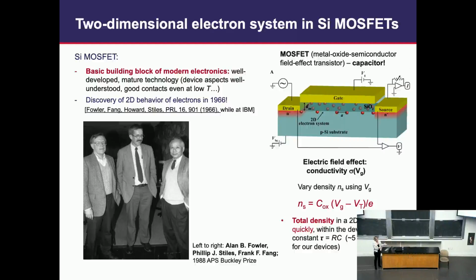And this can be done very quickly. In our case, the longest time is 5 nanoseconds, typically it's on the order of picoseconds. In other words, within our experimental measurement resolution, this is an instantaneous process, okay?